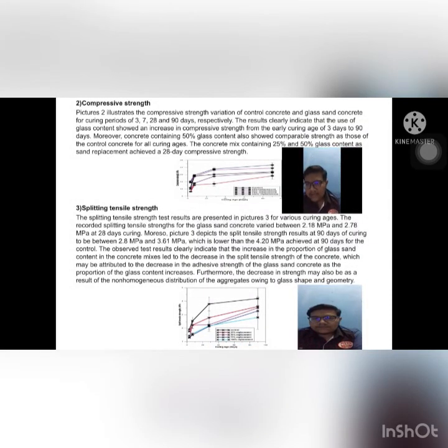Next, compressive strength. The picture illustrates the compressive strength variation of control concrete and glass sand concrete for curing periods of 3, 7, 28, and 90 days respectively. The result clearly indicates that the use of glass content shows an increase in compressive strength from the early curing age of 3 days to 90 days. Moreover, concrete containing 50% glass content also shows comparable strength to that of the control concrete for all curing ages. The concrete mix containing 25% and 50% glass content as sand replacement achieves a 28-day compressive strength.